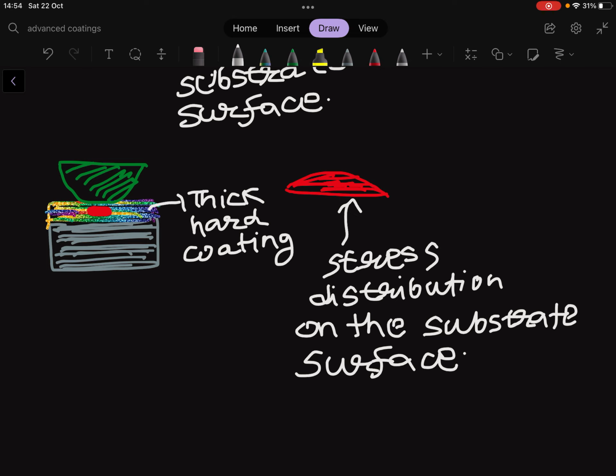So this is definitely not a PVD coating as we said, but it would be a hard layer produced by thermochemical treatment like nitriding or carburizing. In this case, the typical depth is of the order of 100 micrometers, but unfortunately, these layers are not able to provide wear resistance like hard coatings such as nitride and carbide. Now let's discuss the other scenarios.